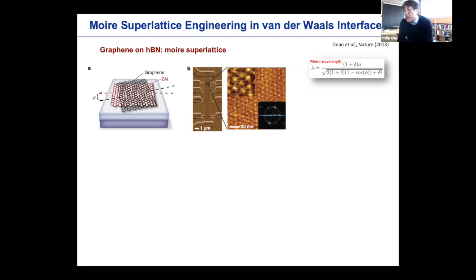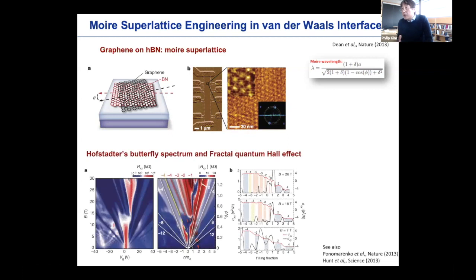Probably the very first demonstration of this Moiré superlattice was graphene on boron nitride, which appeared about 7 or 8 years ago. And then that simple system even led to quite interesting problems, such as Hofstadter's butterfly, seemingly just based on the competition between the periodic Moiré lattice, engineered at something like a 10 nanometer length scale, with a magnetic field whose magnetic length again can be about a 10 nanometer length scale, and that's where the competition of the two different length scales plays quite an important role.